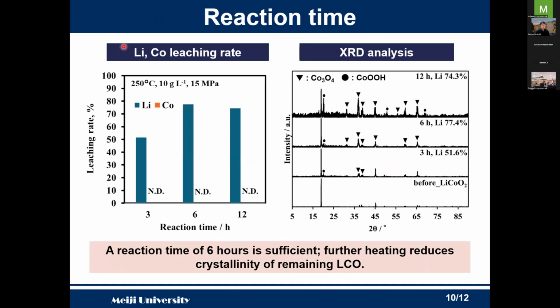Next, we investigated reaction time. The results at 6 and 12 hours were almost the same level, but 3 hours was somewhat lower. So a reaction time of 6 hours is sufficient.